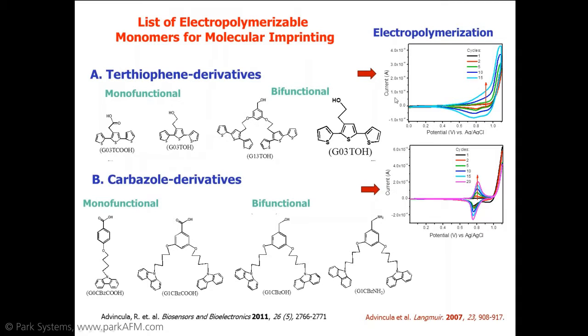And once we electropolymerize them, basically the cyclic voltammogram here shows that they can be cross-linked on the surface as robust films. And the conducting polymer, if you are not familiar with it, basically is a monomer that can be electropolymerized, and once polymerized, it can have either fluorescence or electrical conductivity as part of the pi delocalization and charge carrier generation on this type of polymer.